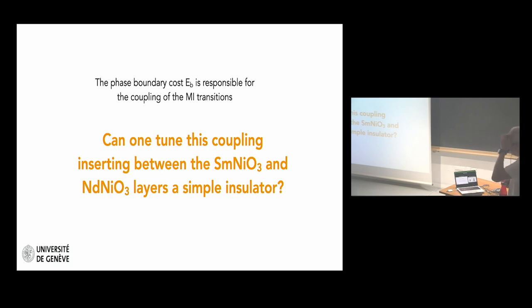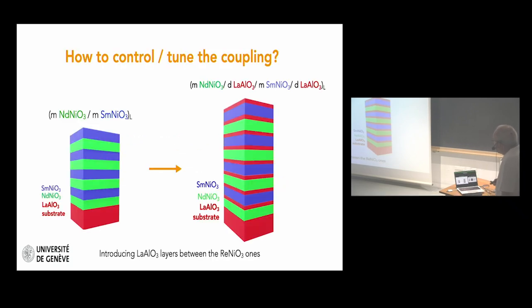The first thing we were thinking is that it would be nice to try tuning this coupling. So how to tune this coupling? We decided to insert something between these layers to see if we could modify this coupling. Since we use lanthanum aluminate as a substrate, the idea was to add, in between the layers of samarium and neodymium, a very thin layer of lanthanum aluminate, a simple insulator. And so the experiment.